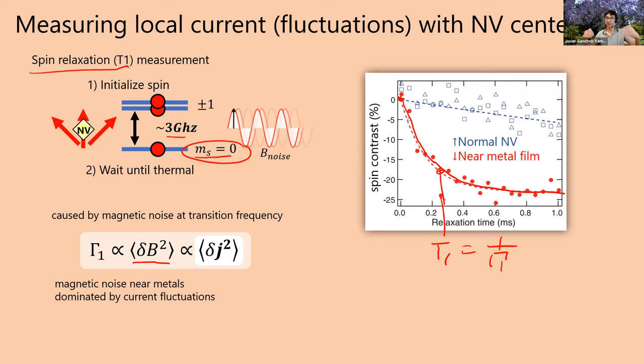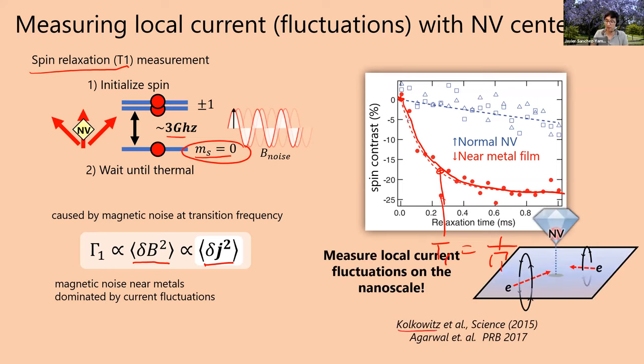that begs a question, okay, what kind of magnetic noise do materials generate? And it turns out that if a material is a conductor, then the noise is dominated by current fluctuations. Okay, so you have charge currents in your material, they're fluctuating around, they generate magnetic noise above the material, and that will cause the NV center to decay. And so this was an experiment done in the Lukin group at Harvard, where they took an NV center and it normally has a very slow decay, but then if you put it near a metal film, then it decays very fast due to the current fluctuations in the metal.